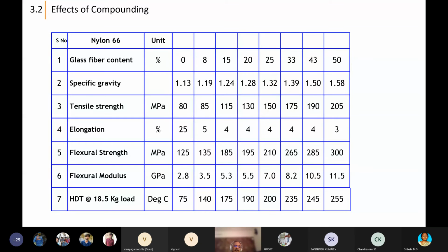And look at the heat deflection temperature at 18.5 kg load. From 75 degrees centigrade for the unfilled, it goes to 255 against a melting point of 265. Nylon 6.6 melts at 260 to 265, and your HDT can go up to 255, short-term duration. And in service, from 70, it will go to 120. So this is the effect of compounding using glass fiber.